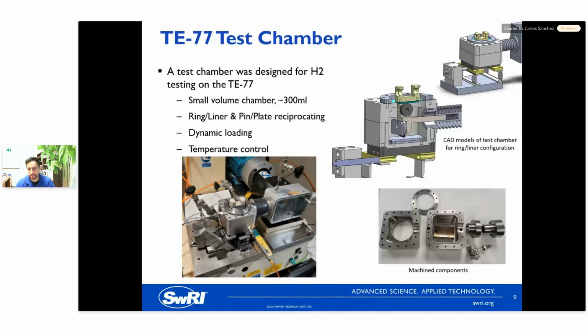There's a number of different seals that go into this to transfer the load, to maintain the oil and maintain the pressure. In this case, it can run at up to about 50 psi of pressure to maintain that hydrogen environment inside the chamber.